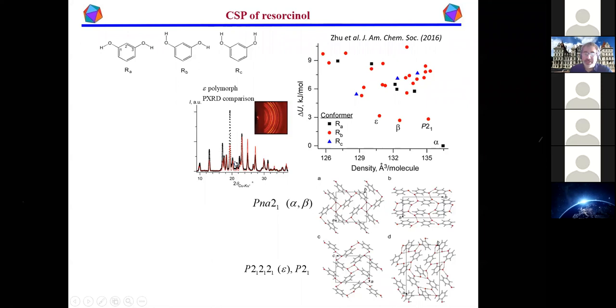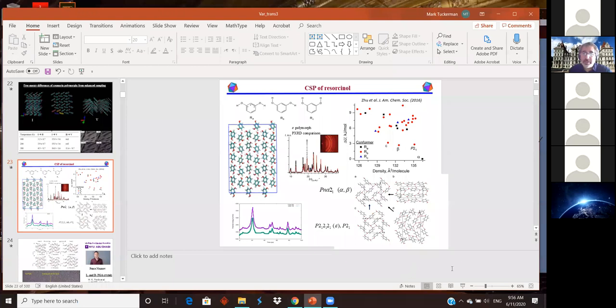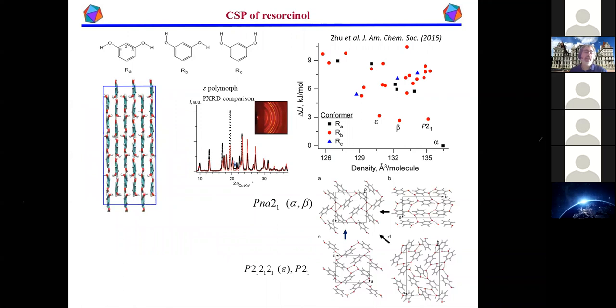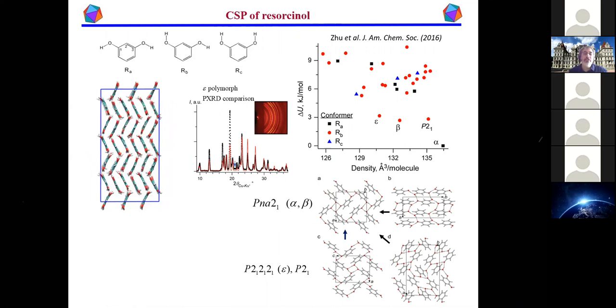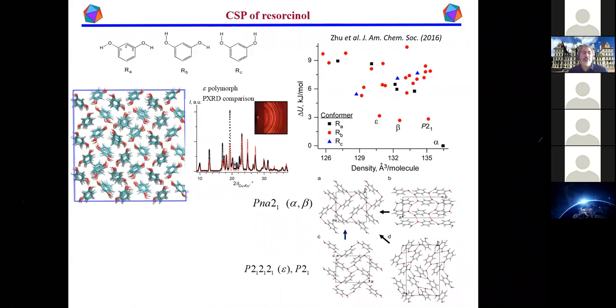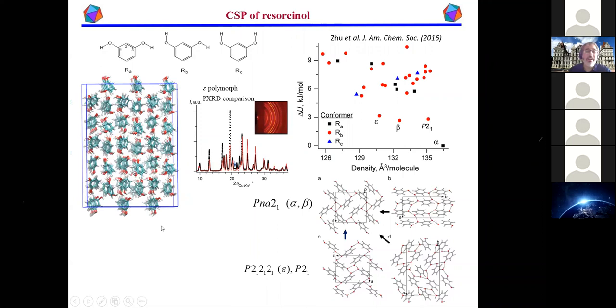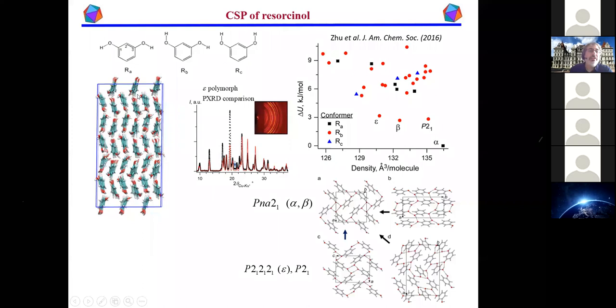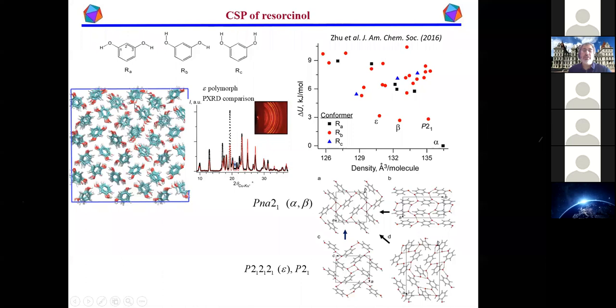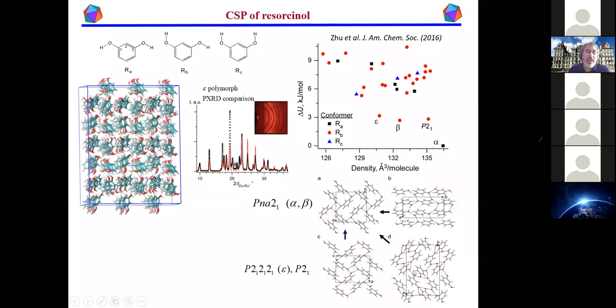But I wanted to show, let's see if I can get this movie to work, the actual exploration using this enhanced sampling approach of the polymorphic landscape. As you watch this movie, you'll see it visit the different structures that you have here. So you can actually get a transition. Of course, you'll always end up in the most stable one ultimately. But this trajectory shows that it produces the conformational change that you need, which is a flipping of the OH group, to go from one of these B polymorphs, epsilon, beta, or P2₁, into the alpha polymorph.